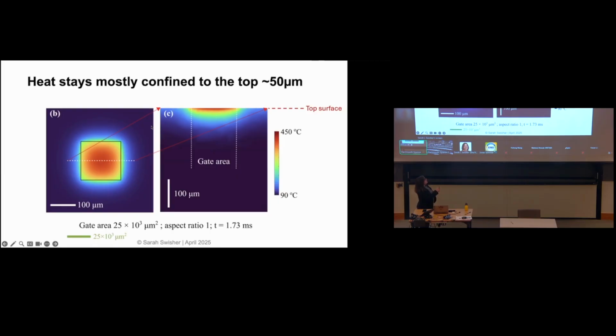So you might wonder why we get this temperature gradient around here on the corners. Why do we get cooler corners, right? Why does size actually matter? And you can think of it this way, right? If you are sitting at the middle of this square, there's going to be a temperature gradient between here and this cool region out here. And the reason for that temperature gradient is because only the square is absorbing the light. The substrate we have selected so that it doesn't absorb much light, so it's not going to get hot. So you know you have a temperature gradient, and we know that heat always flows from hot to cold. So we know that there's going to be a gradient of heat, right? There's going to be a flux of heat flowing outwards from here.